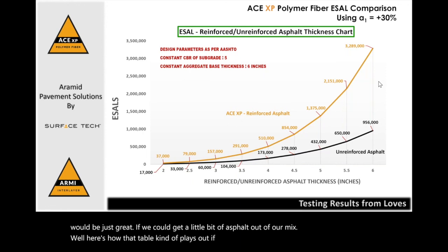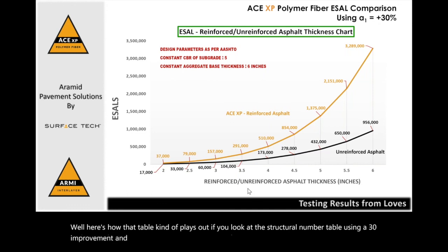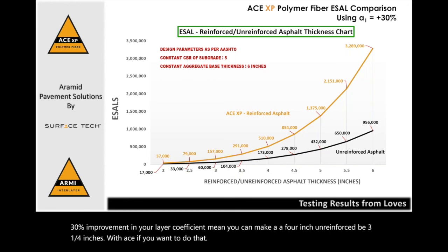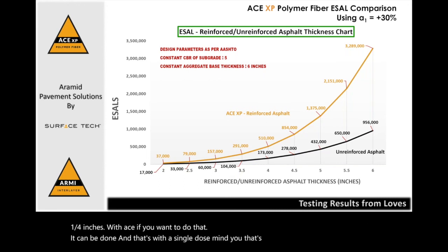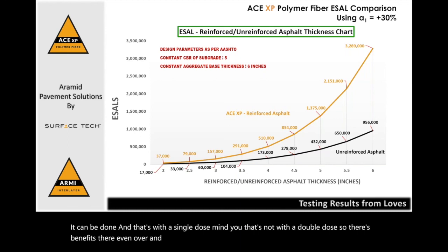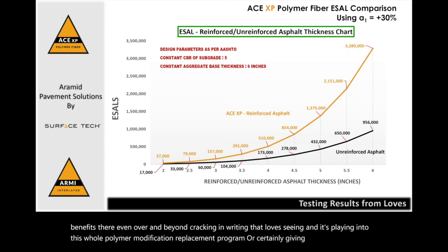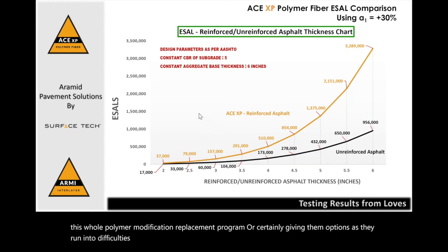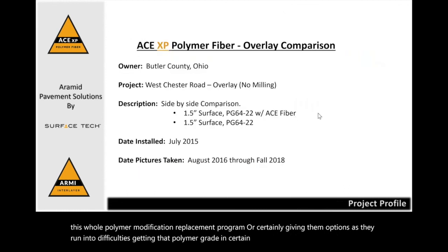If you look at the structure number table, using a 30% improvement in your layer coefficient, I mean, you can make a 4-inch unreinforced be 3 1/4 inches with ACE if you want to do that. It can be done. And that's with a single dose, mind you. That's not with a double dose. So there's benefits there even over and beyond cracking and rutting that Loves is seeing. And it's playing into this whole polymer modification replacement program, or certainly giving them options as they run into difficulties getting that polymer grade in certain rural applications that they have across the country.